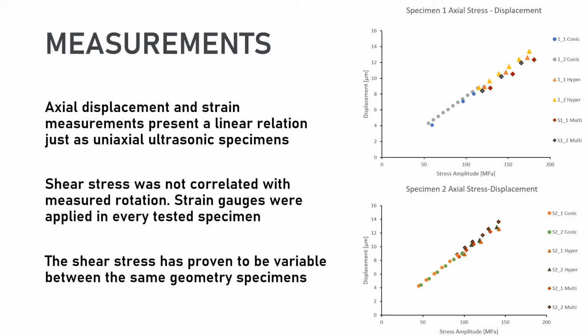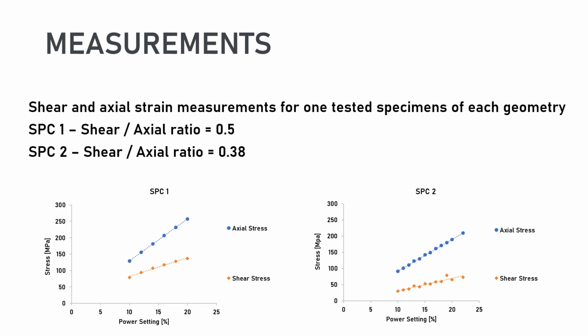Through analysis of the measured displacements and measured strains, we can clearly see a linear relation between the actual stress and the actual displacements, just as in tension compression ultrasonic fatigue specimens. Now, the same cannot be said in the shear and rotation, since we are not measuring at the highest rotation point, and also we observed different shear stress amplitudes between the same specimen geometries. Looking at one example of the strains obtained for one of each geometry, the highest shear specimen we have obtained has a 0.5 ratio, while the other specimen has a 0.38 ratio.